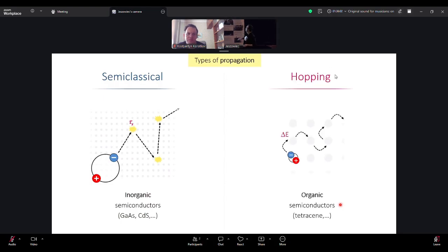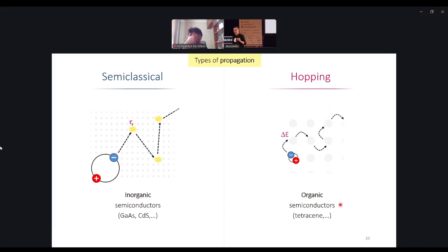On the other hand, for example, you have hopping. Here it's quite faint, but it means that the exciton is localized at a certain spot, and then from time to time there is a hopping process, maybe a tunneling process. Okay. How should temperature impact these two modes? How can we use temperature to distinguish the modes of propagation, be it exciton, be it electron? What do you expect? How should temperature, for example, influence this process?